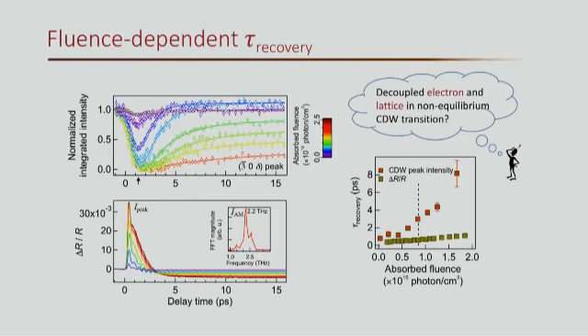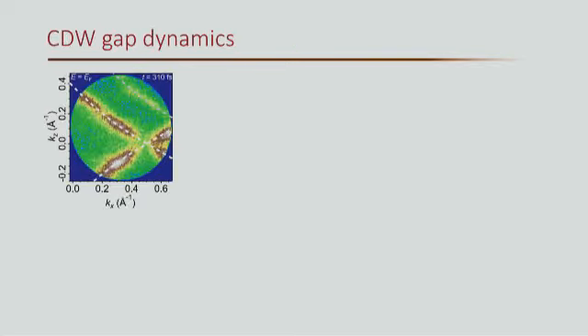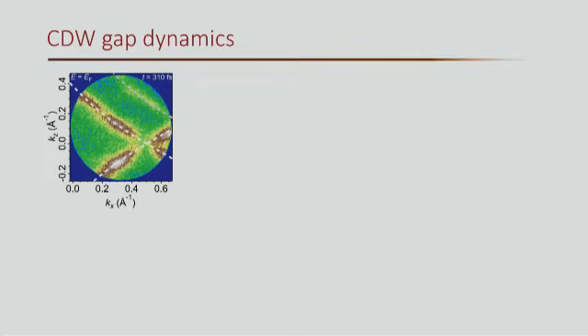So, okay, everything's all good. But what about ARPES? Does ARPES agree with the timescale seen in ultrafast electron diffraction, or does ARPES agree with the timescale seen in transient reflectivity? So here we go. This is the Fermi surface, and we are looking at the field of view in this blue circle. I cheated here a little bit. I didn't put the Fermi surface at before time zero, before the pump arrived, because you can see nothing. As you see, it's pretty much gapped out. So here I put a Fermi surface map at 300 femtoseconds after the arrival of the pump pulse, where you can see partial population of the Fermi surface.